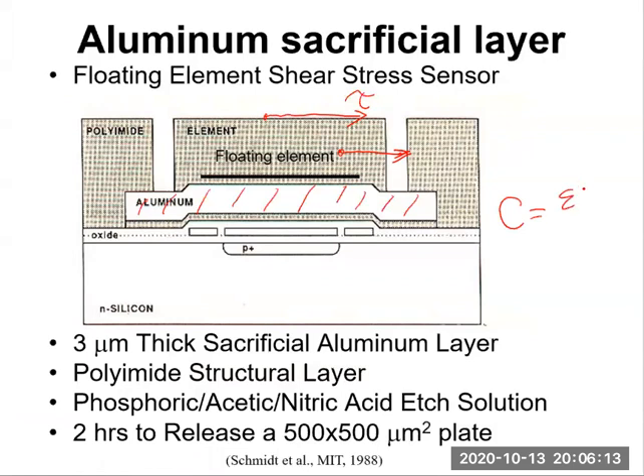Capacitance is equal to epsilon A over D. Right. In this case, epsilon is constant, D, the distance between the two electrodes, is almost constant. A is the overlapping area between the top electrode and bottom electrode. Now, when this floating element moves laterally in response to the shear stress, this overlapping area A changes. Then this capacitance changes. So we can measure the displacement, the movement, by measuring the capacitance. And this is the operating principle of this floating element shear stress sensor.